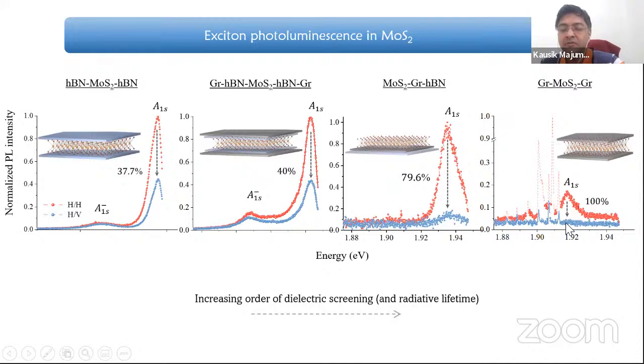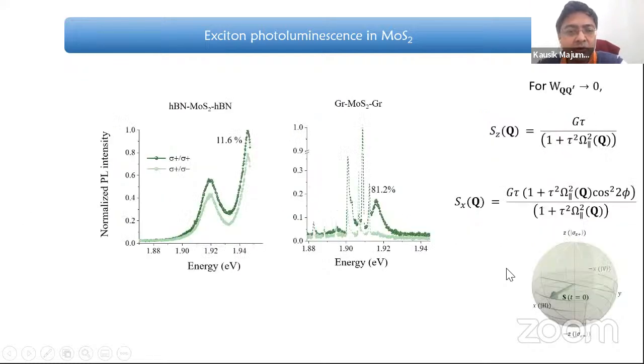So this was really great to observe for the first time, that you can achieve a perfect valley coherence from this kind of highly exchange dominated stacks. To analyze this situation further, before that we measured the circular polarization as well, and you see that in the same stack, graphene encapsulated MoS2, circular polarization was not 100%, but about 81%.